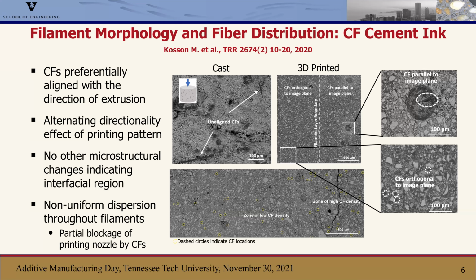Whereas on the right, the only reason we can see the fibers at all is because we have a pore here, which allows us to see further into the image plane, and all the fibers are parallel to the image plane. And that's compared to the cast where the fibers were all unaligned. But interestingly to note, other than that, as we've tried to study the interface, there's no other obvious indicator that there's an interface being crossed here. So there's only really very minimal microstructural changes associated with the interface between these printed filaments.